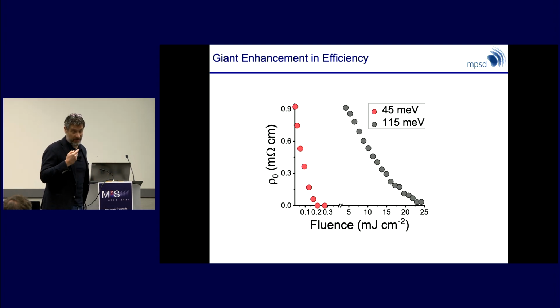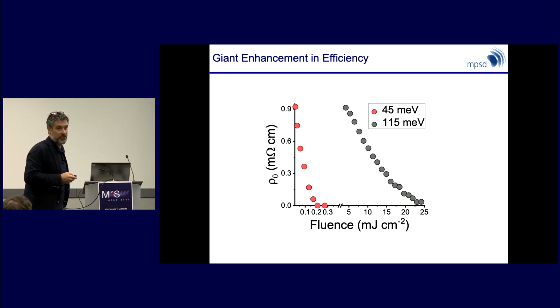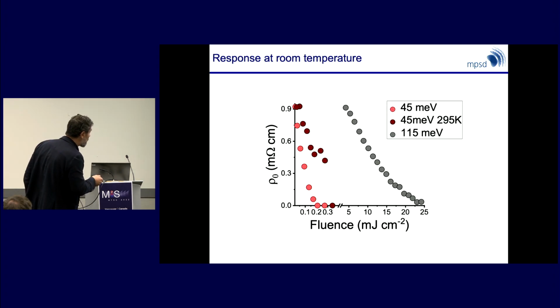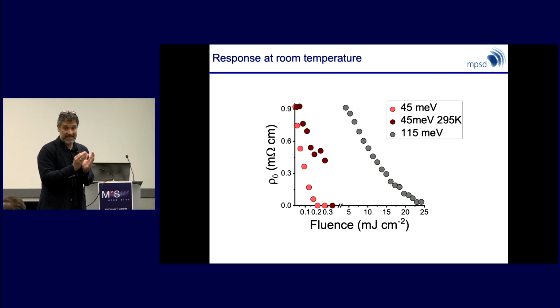And this is also very reassuring because the average heating, and also heating immediately after the pulse, is potentially 100 times smaller. There's less hot carriers. So we have a situation that is much better under control. One of the striking things is that even at room temperature, when you pump at 45 meV, you find optical properties that are suggestive of a zero resistance state at the highest fluences that we can reach. Unfortunately, it's difficult to develop 10 terahertz pulses, and so the furthest we can get to is 300 microjoules per square centimeter. So this is where we are.